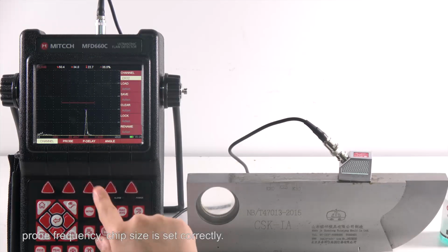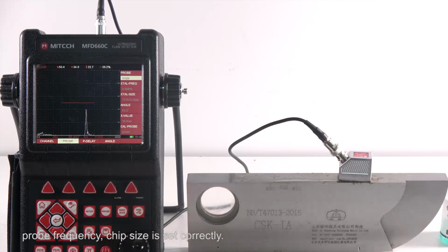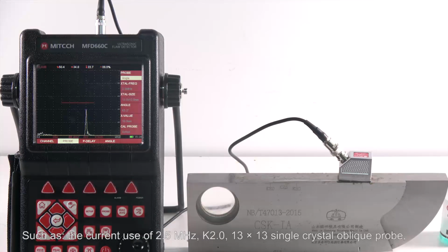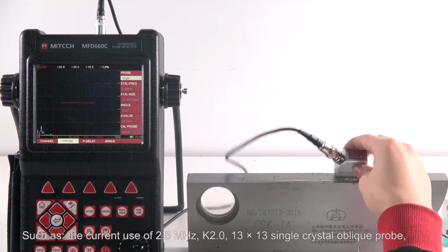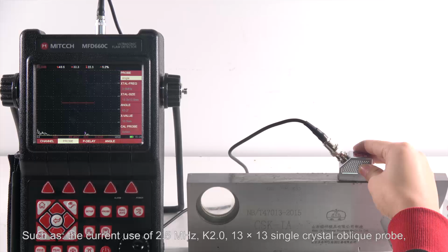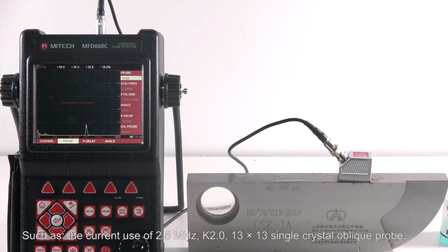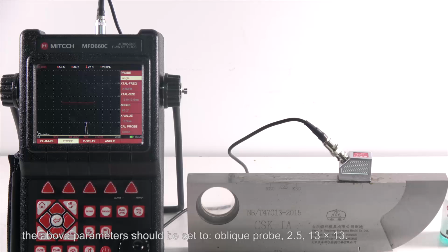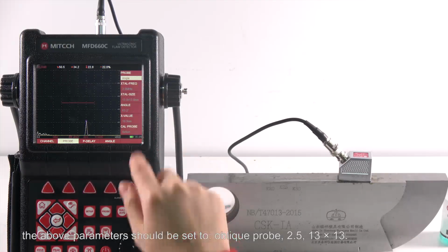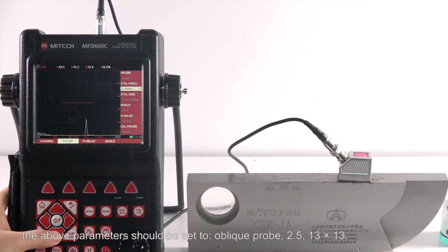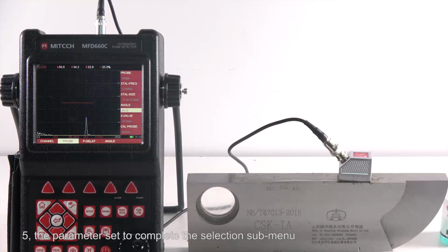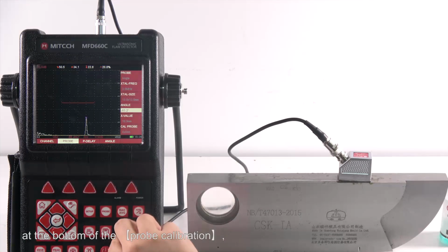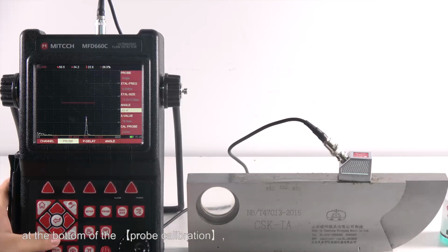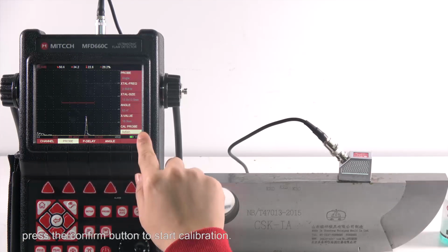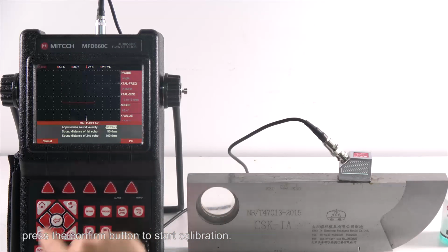Set the probe frequency and chip size correctly, such as the currently used 2.5 MHz K2 13 × 13 single crystal oblique probe. The above parameters should be set to oblique probe, 2.5, 13 × 13. After the parameters are set, select the submenu at the bottom, probe calibration, and press the Confirm button to start calibration.